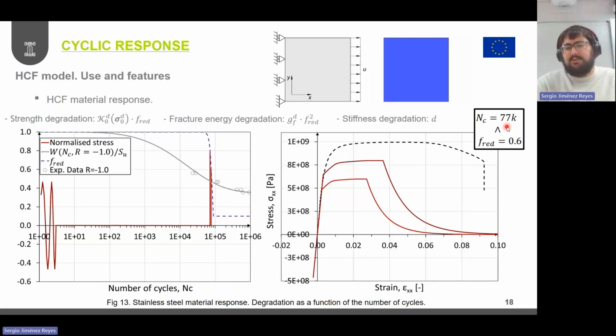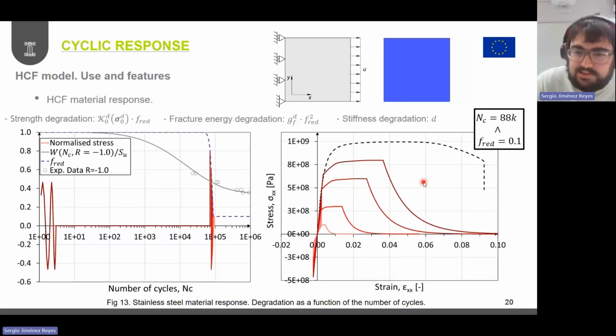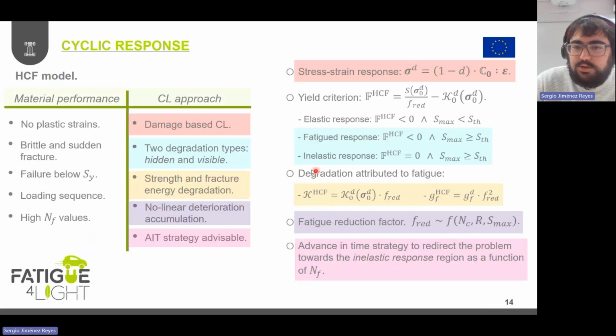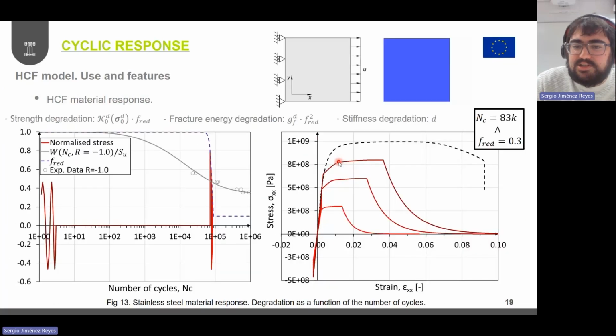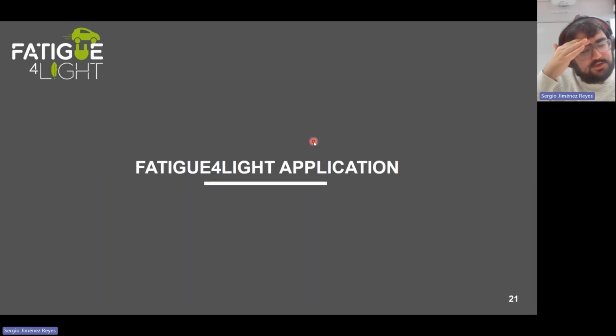So in this case, 77,000 cycles, and then the tensile test. And we can see how the strength and the fracture energy progressively decrease along the simulation. And then I also have these two other cases where, in addition to this strength and fracture energy degradation, we also accumulate stiffness degradation because we are already entering into this final inelastic response of the material where damage is also activated. So not only fatigue reduction factor, but also damage. And this really helps to understand which is the process, or which is the type of response predicted by this type of constitutive model.